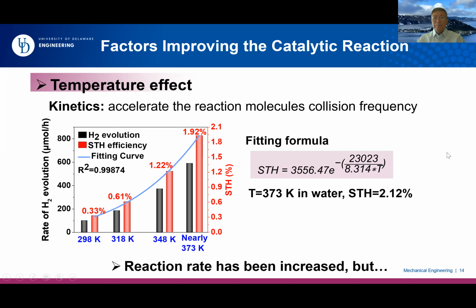From the kinetics perspective, you can easily imagine that it accelerates the reactant molecule collision frequency. Like the experiments show here, you can see that by simply increasing the temperature, you increase the solar-to-hydrogen efficiency, and that curve can be easily fit with this equation. Based on this, if we go up to 100 degrees C, the boiling temperature for water, the solar-to-hydrogen efficiency can be up to about 2%.